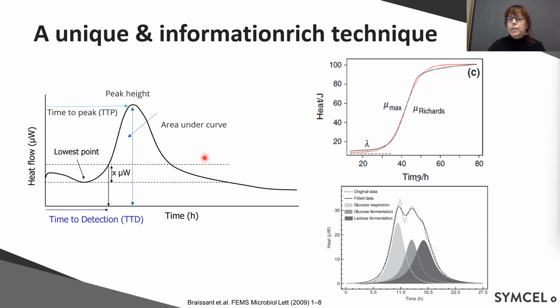Peak height can be interesting, and as you saw on some of the other graphs, you can have several peaks, so you can quantify for several different peaks. You can analyze the area under the curve, so the total metabolic heat that is produced for a certain organism. But then you can also fit data, in this case they have integrated. You can fit different growth models. Usually the growth is best fitted from the beginning because then other metabolic effects will come. But it's possible to use different growth models to evaluate lag phase, growth rates, and, what do you call it, duplication number. No, sorry, maybe not the right word, but how quickly the bacteria replicates.